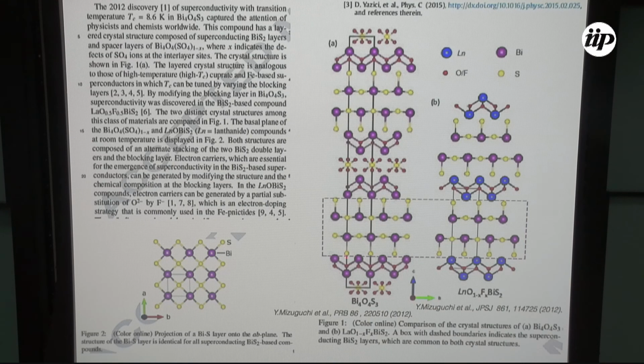And then, the same year, this other family was found, where here you, for example, have lanthanum, and you could dope this material. And, for example, they found that the critical temperature could be increased in this material, applying, for example, 2 gigapascal of pressure, would go to 10.5 Kelvin. And with lanthanum, they could actually prepare good single crystals. So many other experiments were available and results obtained.